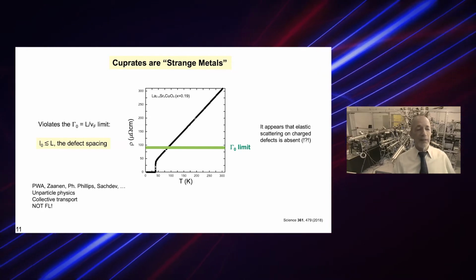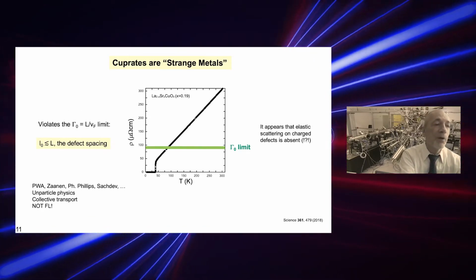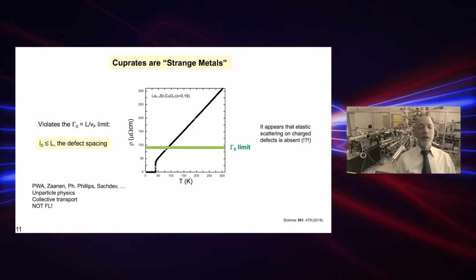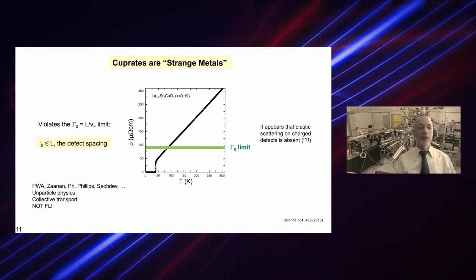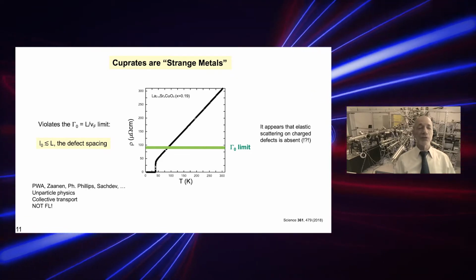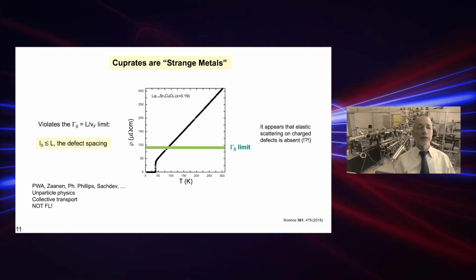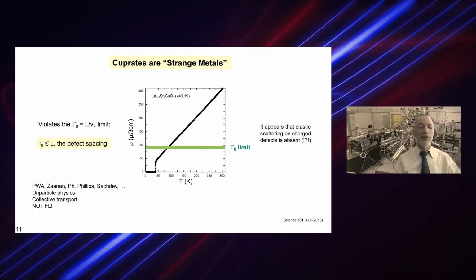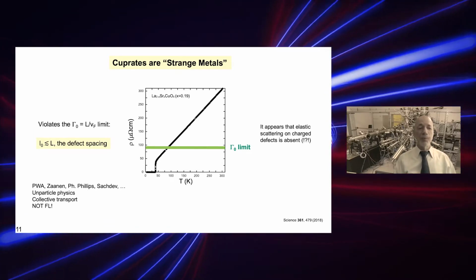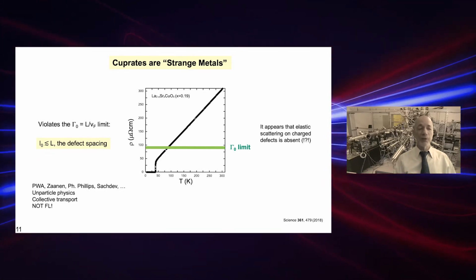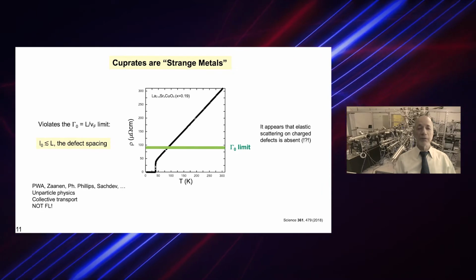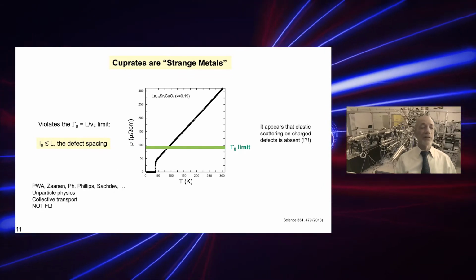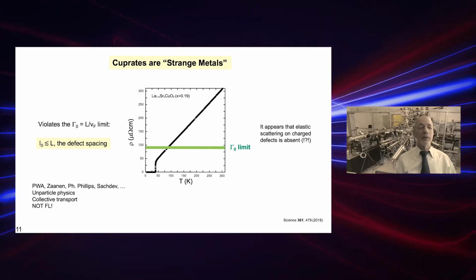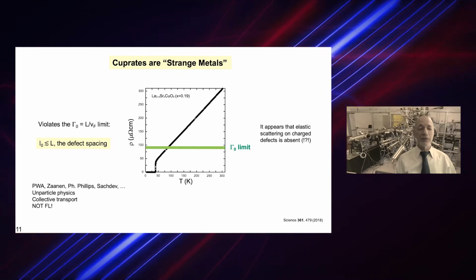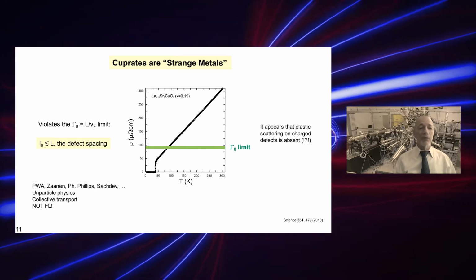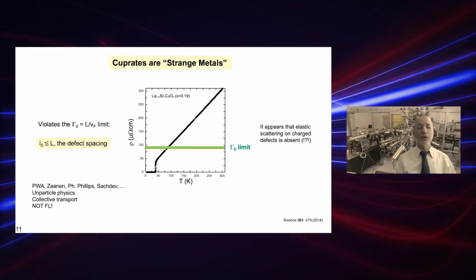There is another, maybe even more upsetting discrepancy, and that is that in a Fermi liquid at low temperature, phonons and other excitations should die out, and the electrons only scatter elastically on lattice defects and impurities. Now, lanthanum strontium cuprate contains strontium dopants, which are charged impurities, so they should be pretty strong scatterers. The electron is charged and there is a Coulomb repulsion or attraction. At optimal doping, the average spacing between these charge defects is about 8 angstroms. One would not expect the mean free path to get much longer than that.